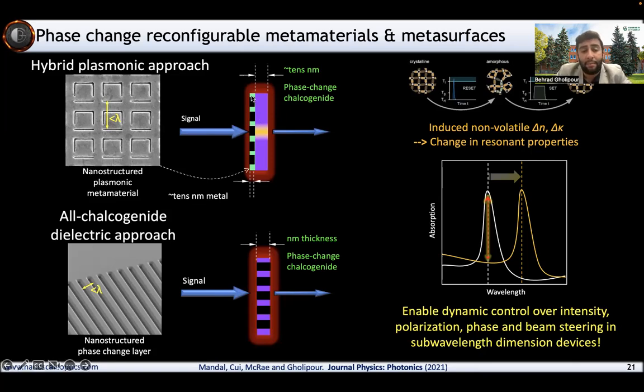We either nanostructure a plasmonic metal, and by nanostructuring the plasmonic metal, we create these nice resonances, optical resonances, that we then put a nice phase-change chalcogenide right next to. So a layer of a phase-change chalcogenide is deposited next to your plasmonic metal that's been nanostructured to have a particular resonance at a wavelength of interest to you for your applications. And by changing the refractive index of this material system based on that phase transition, which I just showed you in a couple of slides back, we can create these tunable resonances, so we can switch the resonance from one wavelength to the other, and this creates very large optical contrast at our operation wavelength that wouldn't be available naturally in the unstructured material.